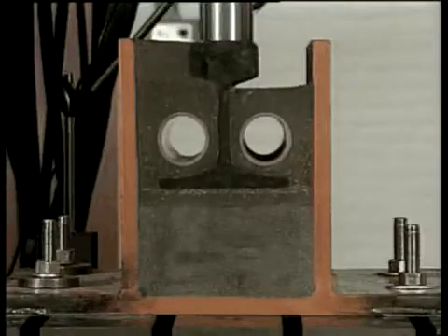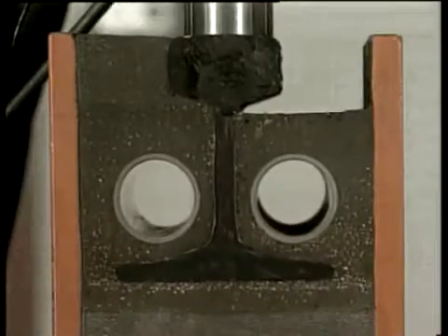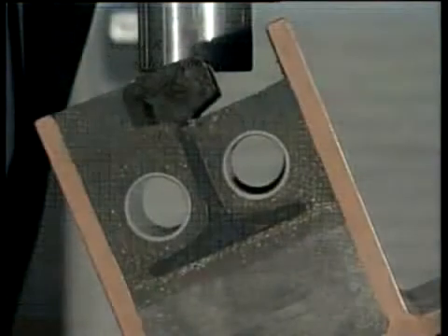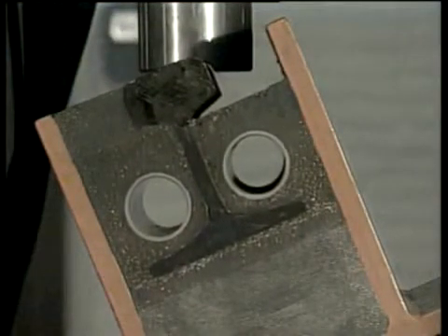There is thorough testing of the trough containing the track section of embedded rail incorporating cork-bearing polymer Corkelast. The more the Corkelast layer is compressed, the more vibration and noise are absorbed. Even at an angle of stress of 22 degrees and a burden of 3 million alternating loads, the adhesion between the Corkelast and the steel trough remains entirely intact.